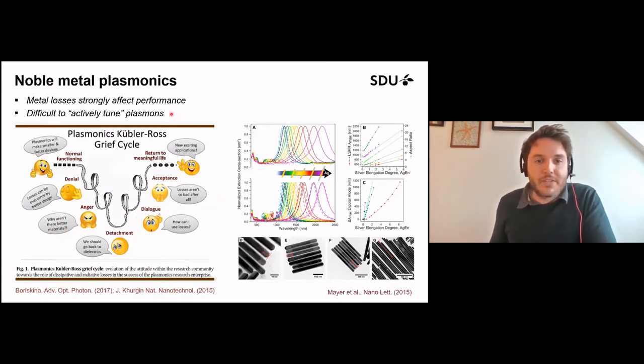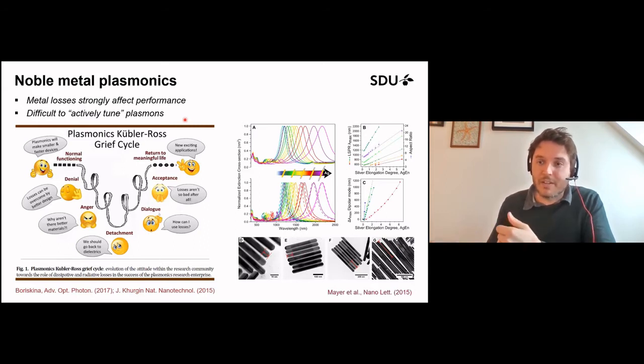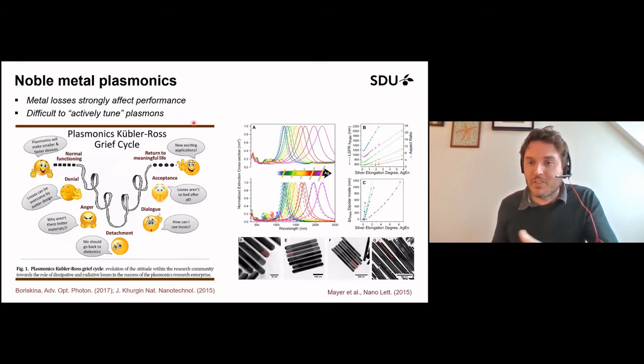But the other disadvantage of noble metal plasmons is that, I mentioned that you can tune their resonances by changing their composition or geometry, which is fine when you're fabricating them. But then if you want to make a device that can be tuned on and off, actively switched, this is a problem because you can't easily change the size of your metal particle, right? So this is another limitation that we face in this field.